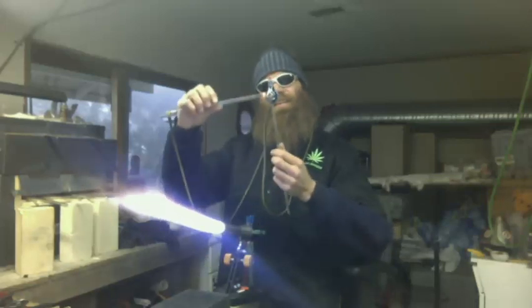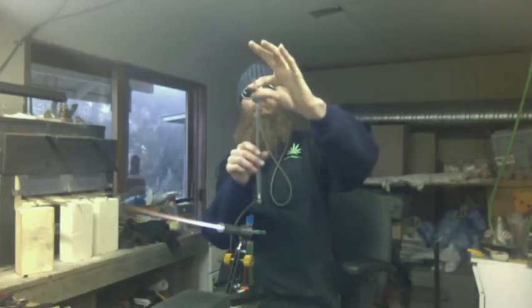So, there I reverse the axes. Often we call these reballs or reverse balls. So all I've done, there you can see this, it used to be this way. Now it's this way. I've got it on a 90 degrees. So now all the colors are at the end of the ball, see? And this is a fade to clear ball, so all the colors on one end, all the clears on the other. Really fond of the fade to clear style. That's a nice effect, and it sure is tricky. The clear behaves one way, color behaves another. Mostly in viscosity, the color is much stiffer. And each color has its own viscosity level, too. White's much creamier than black, for instance.